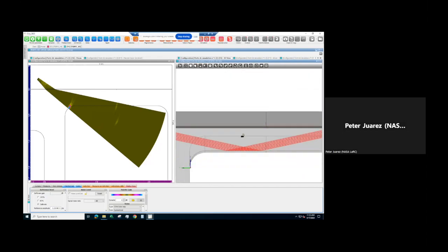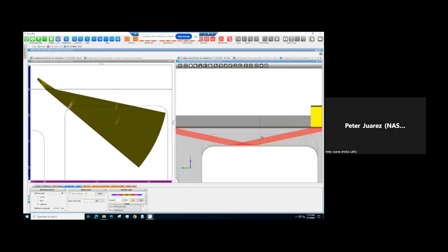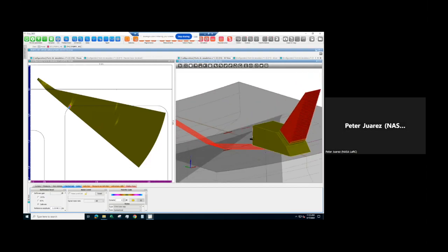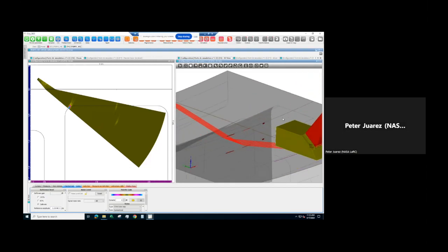And we tested several different thicknesses of adhesive, and the answers were mostly all the same. But this is the smallest one we tested. And even with the smallest one, this is the same indication. Let me put it back over there. There we go. So both these images have been scaled to the exact same amount, and you can see a drastic reduction in the signal quality just from a very thin layer of adhesive.